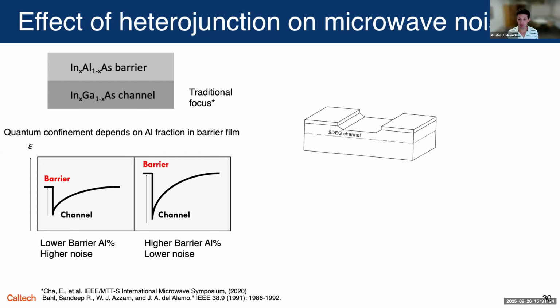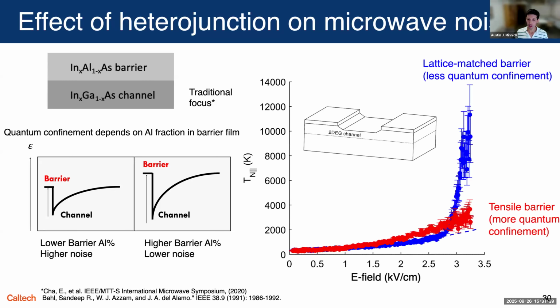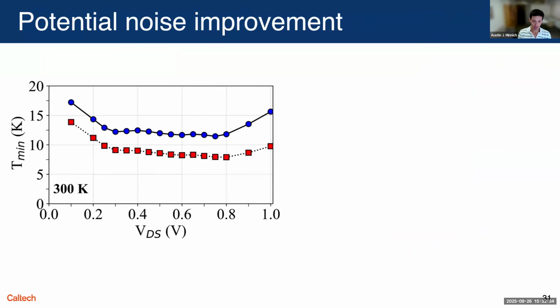We have some measurements which I'll only present very briefly, but we used ungated structures like what you see here. And this is a measurement of noise temperature versus E field in these structures. And you can see that in the blue case, which is a lattice-matched barrier, lower quantum confinement, above some field, these electrons get hot enough to hop out, and there's this rapid increase in noise in the blue symbols. But in the tensile barrier, where the quantum confinement is better, although the initial noise looks a little bit bigger, you'll notice that it doesn't experience this very rapid increase at the same E field compared to the blue case. So we interpret this as the quantum confinement is able to suppress the hopping of these electrons out of the channel. So this is some evidence that this effect is actually present, and that suggests a path forward to make HEMTs, to manipulate that epitaxial composition.